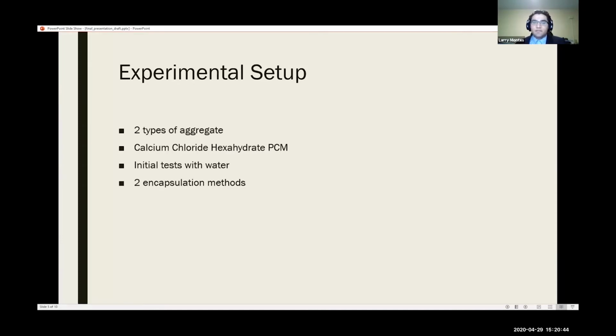For the experiments, we performed tests on two types of aggregates, 3/4 inch Norlite and 3/8 inch Norlite. Norlite is a type of expanded shale aggregate. For the PCM, we had calcium chloride hexahydrate, which possessed a phase change temperature at 26 degrees Celsius, or around 79 degrees Fahrenheit, which is fairly close to room temperature.